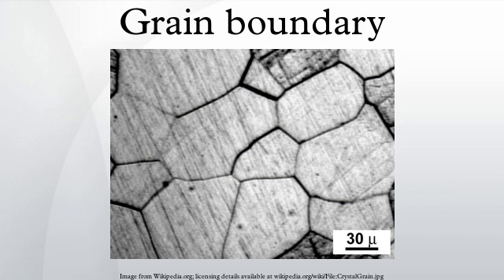In comparison to low angle grain boundaries, high angle boundaries are considerably more disordered, with large areas of poor fit and a comparatively open structure. Indeed, they were originally thought to be some form of amorphous or even liquid layer between the grains. However, this model could not explain the observed strength of grain boundaries and, after the invention of electron microscopy, direct evidence of the grain structure meant the hypothesis had to be discarded. It is now accepted that a boundary consists of structural units which depend on both the misorientation of the two grains and the plane of the interface.